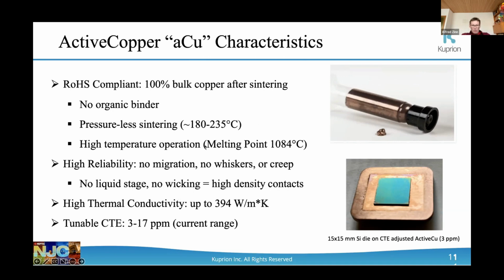Once it's fused, it reverts to bulk copper, and then its melting point goes back to 1084 C. There's no migration, no whiskers or creep. It's actually very, very resistant to migration. We have done some interesting tests there. Another interesting feature is there's no liquid stage, so there's no wicking. So you can have contacts very, very close together, very fine pitch. And the CTE so far, we have explored the range from as low as 3 and 17 as the standard copper CTE.